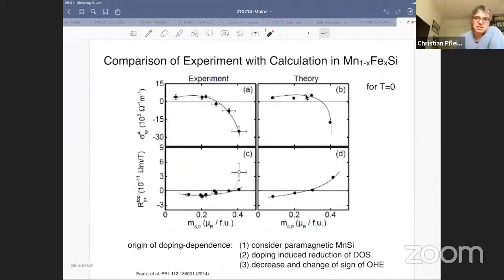And with this slide, I just want to show you, without going into the details, that actually there's excellent agreement between experiment and theory of this anomalous Hall contribution and this topological Hall contribution. And that already showed us that DFT calculations give a lot of valid information about the Fermi surface, and that, in a nutshell, one can think of the spin split state, even though it's complicated, as just like a rigidly spin split state.